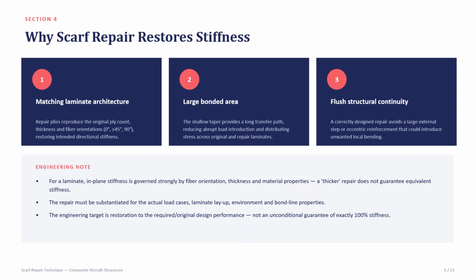And why does scarf repair restore stiffness? First, it matches the laminate architecture. Its repair plies reproduce the original ply count, that is, the thickness and fiber orientations like 0 degree, 45 degree and 90 degree. This will restore the inherent directional stiffness. Second, the large bonded area: the shallow taper provides a long transfer path, reducing abrupt load introduction and distributing stress across the original and repair laminates. And third is flush structural continuity. A correctly designed repair avoids a large external step or eccentric reinforcement that could introduce unwanted local bending.